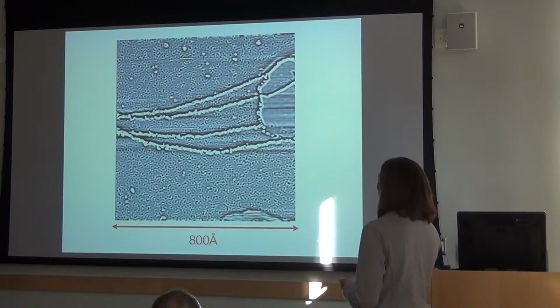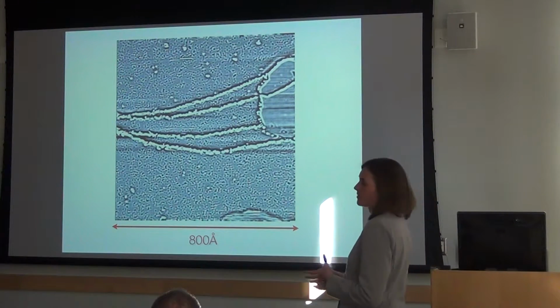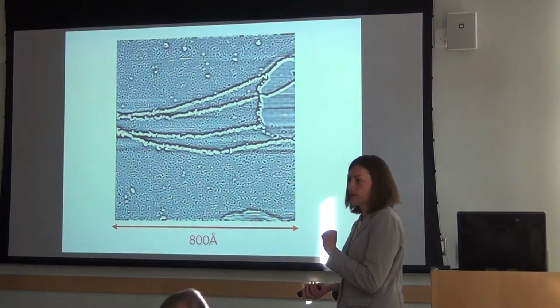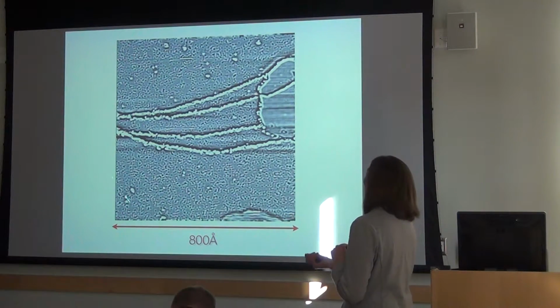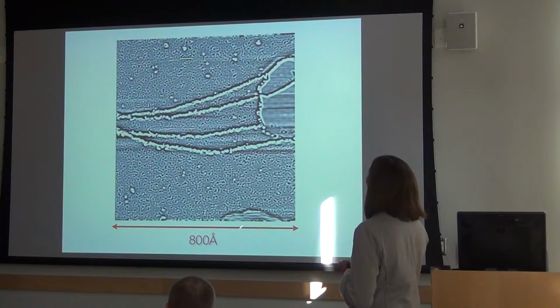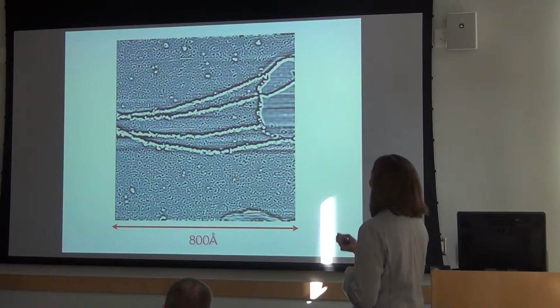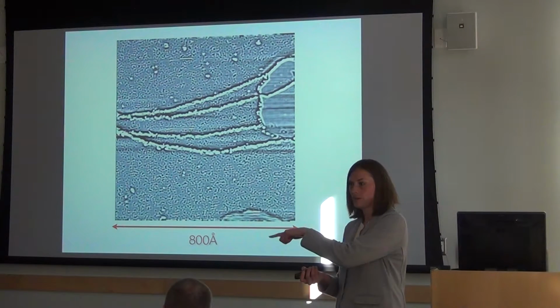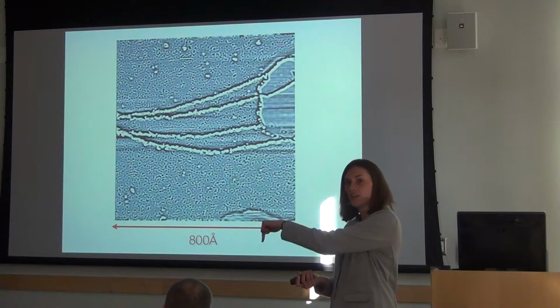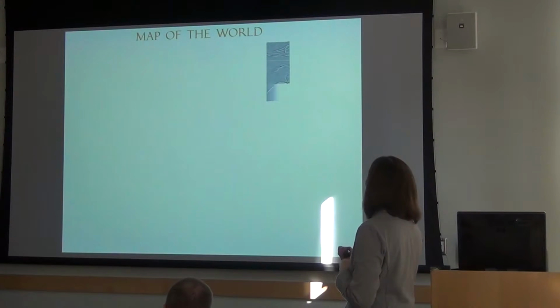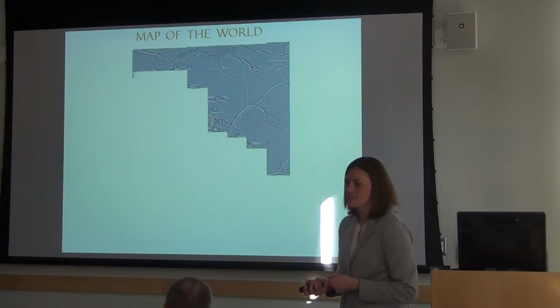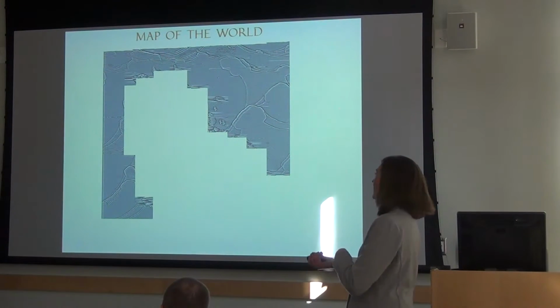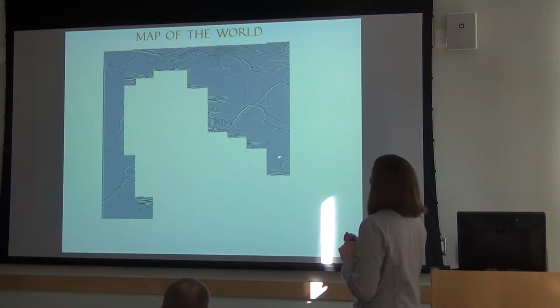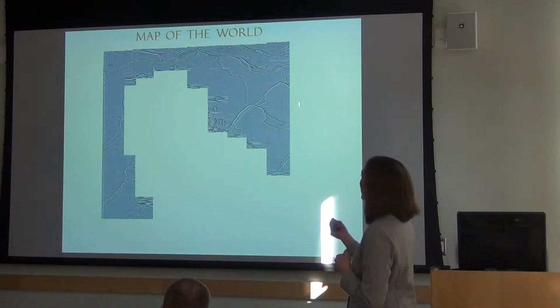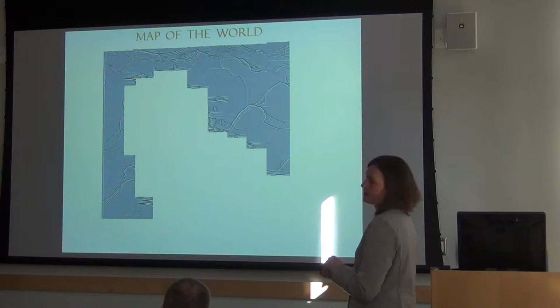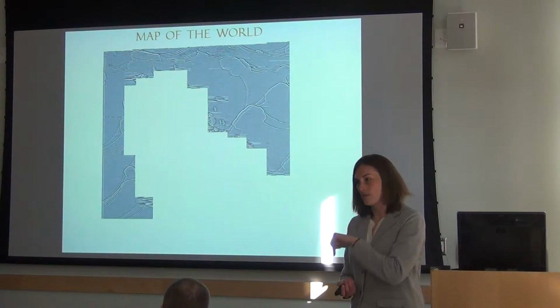So this is a pretty big image. This is the largest image we can take at one time with the STM at helium temperatures. And if we want to map out what the area looks like, then we need to take an image and then move the tip over and take another image and then move the tip again and take another image. So you can do this and you can get sort of the map of the world according to the STM tip. You can take lots of these 800 angstrom images and put them together into a map. And this is the entire area that your STM tip can access at one time.